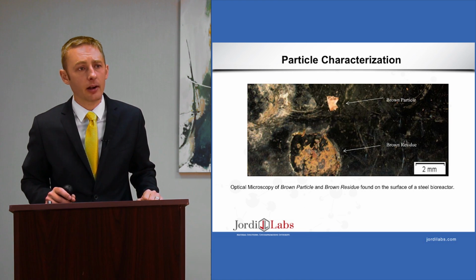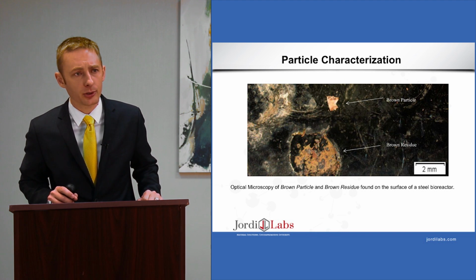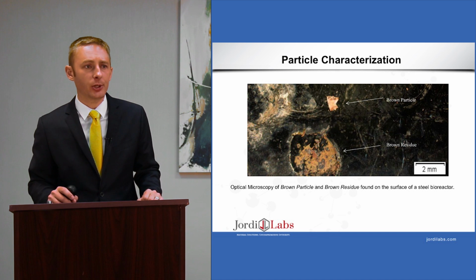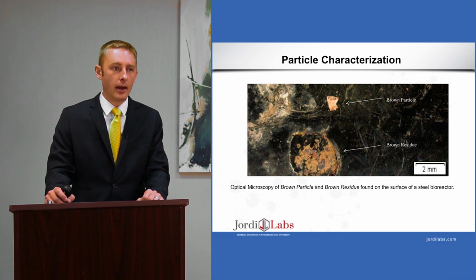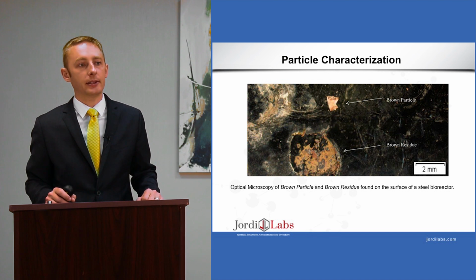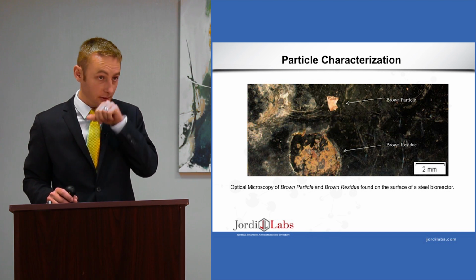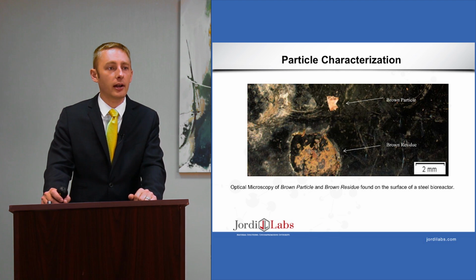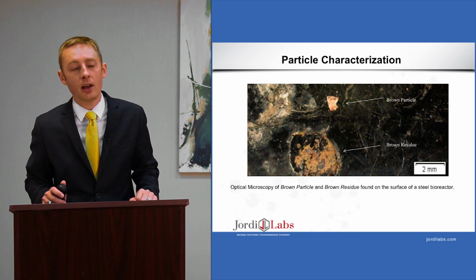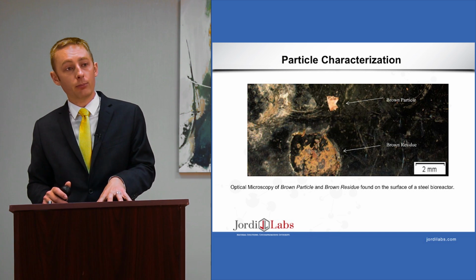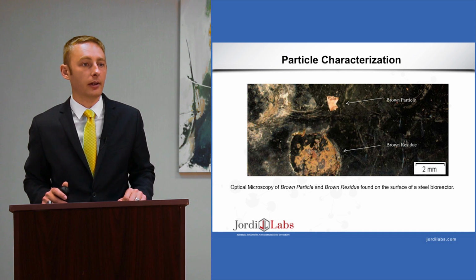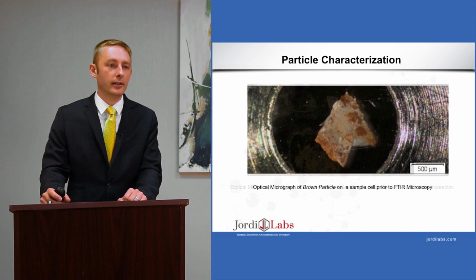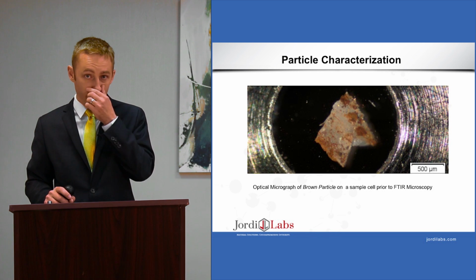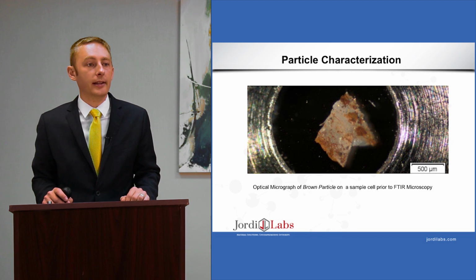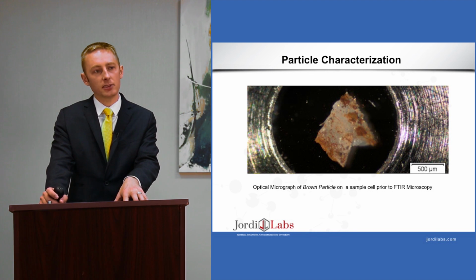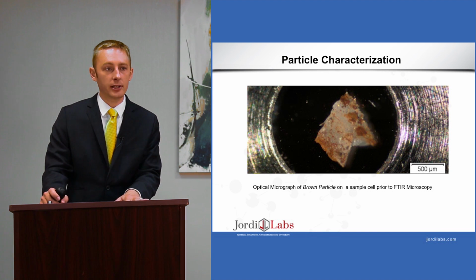And so here's a case study where we go over some example data for particle characterization. In this particular case, I believe it was from a bioreactor. Yes, it was from a steel bioreactor. And they gave us a residue and a brown particle. And so the samples in this case are descriptively labeled as brown particle and brown residue. And so here's an optical micrograph of the brown particle and the brown residue with a 2 millimeter optic bar on it. And then here's a zoom in on the optical micrograph of the brown particle. At a closer scale, it looks like a white material with some brown residue on it.